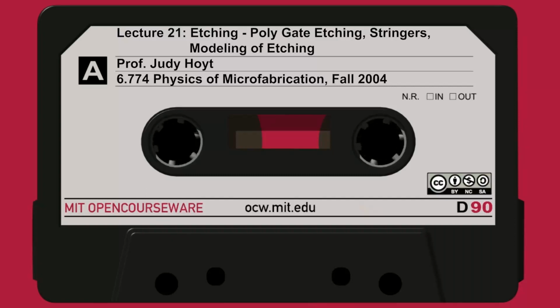The solution to this is, well, you could say, don't use an etch that's so selective to oxide, but if you want to stop on SiO2, you wouldn't want to do that. The solution is the very first part of your etch step should be a breakthrough etch, where you make sure you break through all the native oxide, and then you continue on down. So it gets a little tricky when you start etching multiple materials, or when you have to think about the fact that there may be materials on the wafer you don't know about. Native silicon dioxide may be there. Even if you didn't put it there, it grows there automatically on the wafer. So you have to remember to get it off the surface before you use a highly selective etch.